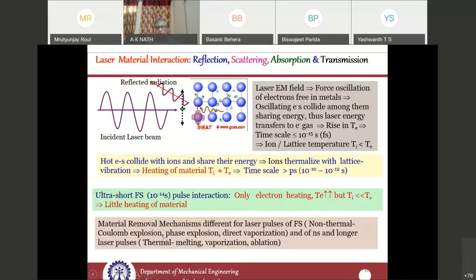But when you consider how the material is going to get heated up and how it is going to remove the material, the removal process in case of femtosecond laser is through phase explosion, Coulomb explosion, or direct vaporization. In case of nanosecond and longer pulse, the material is going to get removed by thermal effects like melting, vaporization, and ablation.